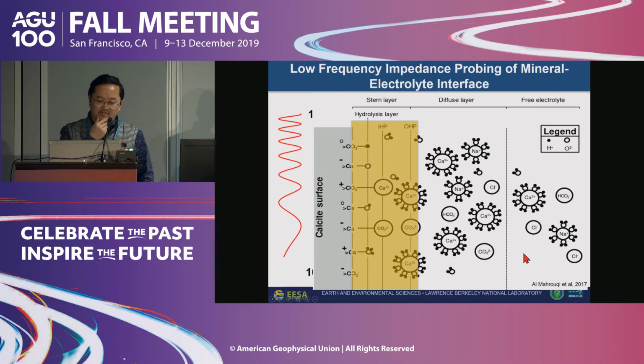Talking specifically about calcite, we are using this technology to look at the behavior at the interface, particularly the Stern layer close to the mineral interface. This is a simple structure of the electrical double layer. A lot of existing techniques look at, for example, the zeta potential at the shear plane, which more or less overlaps with the zone of perturbation we can probe with the low frequency method.